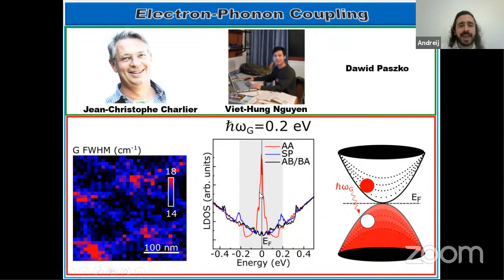And look, at the AA site we have a very pronounced peak, at the SP we have two smaller peaks, and at the ABBA we have no peaks. So this tells us that the probability for phonon absorption is higher at the AA and then the SP sites, just like we observed experimentally. So the higher the phonon absorption, the higher is the phonon width.